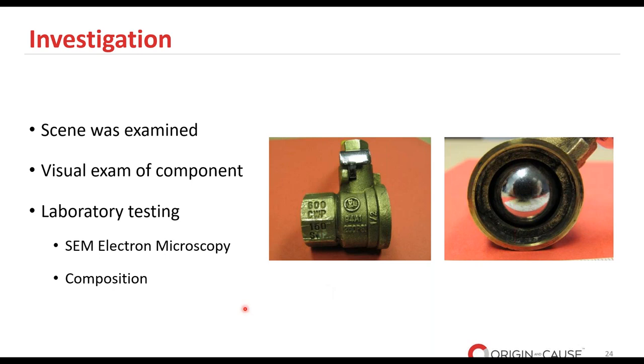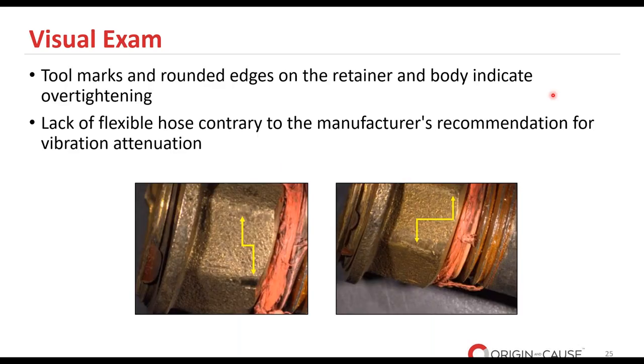So during the visual examination phase, some distinct features became apparent to us. The presence of tool marks and rounded edges were clear indicators of over-tightening, which is a significant concern. Over-tightening can place additional stress on a component, making it more prone to failures. Also, a concerning omission was noted, and this was the absence of a flexible hose, so we can see it's connected to a rigid pipe. The use of a flexible hose was recommended by the manufacturer in this case. And these types of flexible hoses play an important role in reducing vibrations and also mechanical wear.